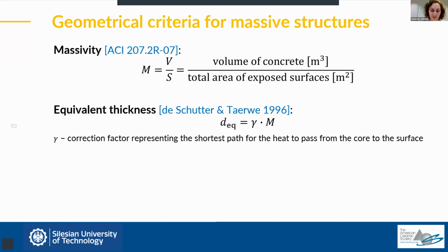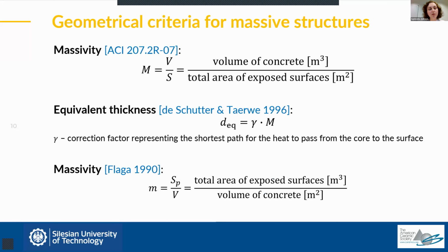And a similar measure was proposed by Flaga, a Polish researcher, which is very similar to the massivity definition from ACI. The only difference is the inverse approach, even though if we go into detail in understanding these two measures, we will see that the definition of the exposed surfaces in these two approaches is a little bit different. Also, what is important is that the proposal of Flaga is the only proposal which is actually quantifiable, because not only does it allow us to calculate the massivity, but it also allows us to classify structures according to the massivity. So it can allow engineers to do some preliminary analysis to define if a structure is susceptible to thermal cracking or not.